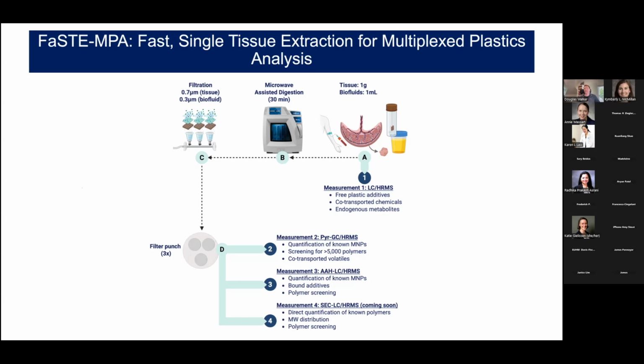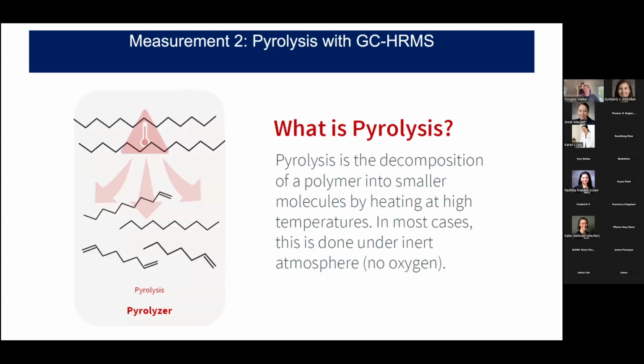What that does is it takes the polymers that are present in those microplastics and depolymerizes them, releasing additives and allowing us to measure the individual monomers. And then the last approach that we have all the infrastructure for, but we haven't started method optimization for yet, is using size exclusion chromatography interfaced to a high resolution mass spectrometry system. And this will actually allow direct quantification of known polymers. All these other methods we have are called indirect methods because we're converting the polymers into something else before we're measuring them. But I'd like to next focus on pyrolysis, which has been one of the most commonly used mass-based measurements for microplastics and is really emerging as one of the key technologies that we're using in our lab.